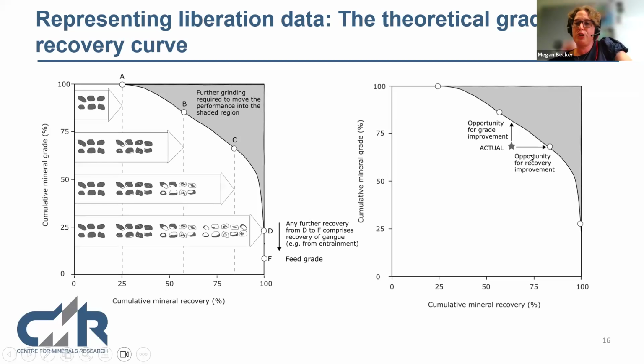So what happens if you plot this curve with plant data? Say you look at a concentrator and the star is the point where the concentrator is operating. We know that according to that theoretical grade recovery curve, the opportunity for grade improvement is this, and the opportunity for recovery improvement is that. Or I can go diagonally to the right, and I can get a bit more grade and recovery. I know, though, that it's impossible to get anything into this area. So if I was doing a reagent trial or something, I cannot get a grade recovery in this dark gray area. It's impossible. The only place you can improve is up to that curve.